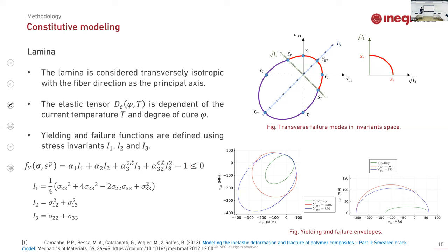For the transverse lamina, since it is orthotropic and the plasticity is only developed in the transverse direction, not in the fiber direction, it is a very complex model proposed by Professor Pedro Camanho and Matthias Vogler that is based on the stress invariants. None of the stresses in the fiber direction are considered, only the stress state in the transverse direction of the material.